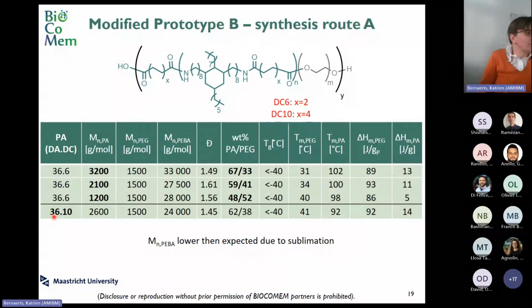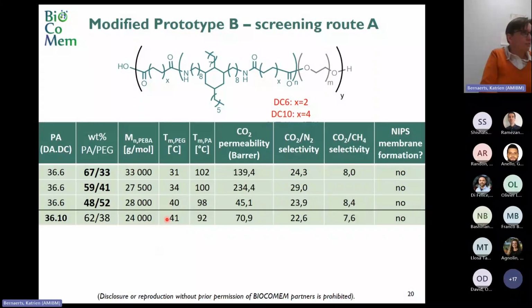Further, we made a variant where we replace sebacic acid with adipic acid, and we will compare the results. Now, what we observed during the synthesis is that the molecular weight of the PEBA that we obtained is lower than expected because of some sublimation. Nevertheless, we tested the membrane performance, and Oana will explain this slide.